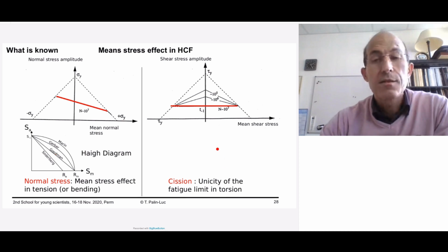But on the opposite, if you look at the shear stress amplitude depending on the mean shear stress in high cycle fatigue, so around 10 to the 7 cycles and more, there is no effect. You can see a plateau here. The stress amplitude in shear is not affected by the mean shear stress, approximately up to a maximum shear stress equal to 80% of the yield strength in shear. So this is very important because all the simulations consider these two effects.